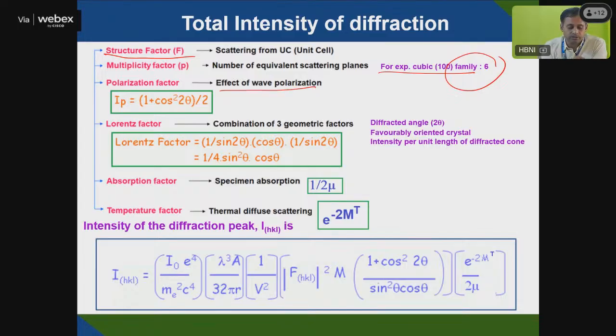Then the polarization factor, the wave polarization, comes into the picture. And then the Lorentz factor, the geometric factor, which depends on the alignment, the arrangement of the lens and slits and so on. Then there is the absorption factor, because the sample may get heated; as I told, some IR radiation can be emitted, so the sample can be heated. That will be 1 by 2 mu. Then there are the temperature effect and diffuse scattering, the Debye scattering. So the total intensity I is the product of the polarization factor, the structure factor and all the other factors together. This is your polarization factor, this 1 by 2 mu is your absorption factor, and this is your diffuse scattering. So this is the total intensity.